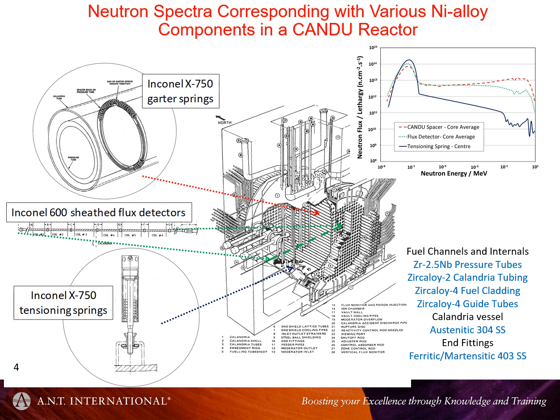So in the CANDU reactor, it runs on natural uranium, has a very high thermal flux because of that, and therefore can operate and generate fission. And neutron economy is very important. So anything which is nickel or steel in the core, even though the calandria vessel itself is 304 stainless steel, anything in the core is minimized. The amount of mass in the core is minimized. Springs are tolerated because nickel alloys are good springs. And flux detectors are also tolerated because they can be taken out after a short while. They can be easily removed, but they'd only last for 5 or 6 years. At the edge of the core, there are these tensioning springs, and that's another story. They have some very interesting effects as well.